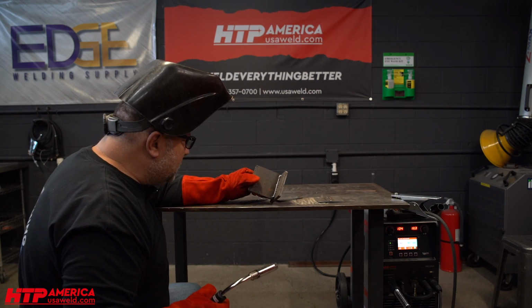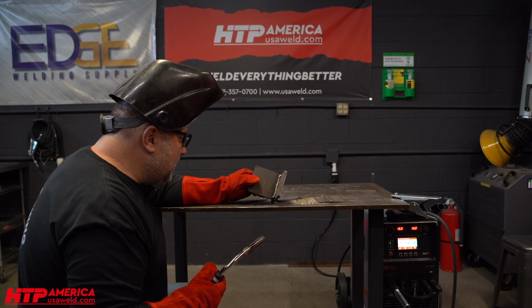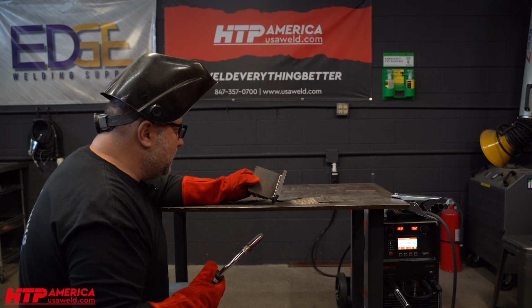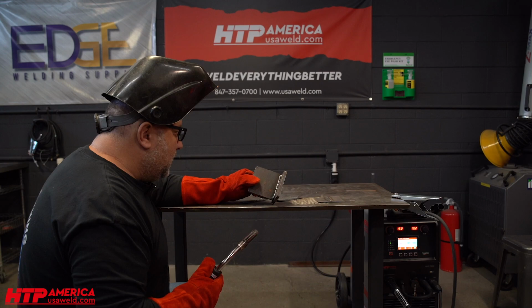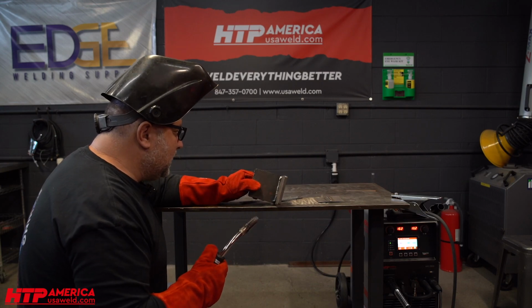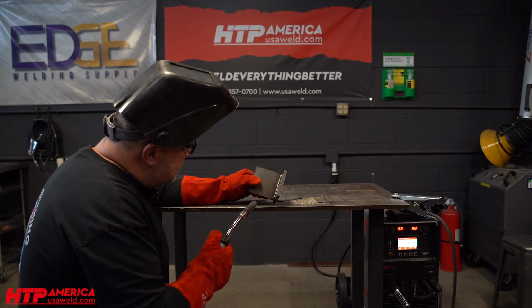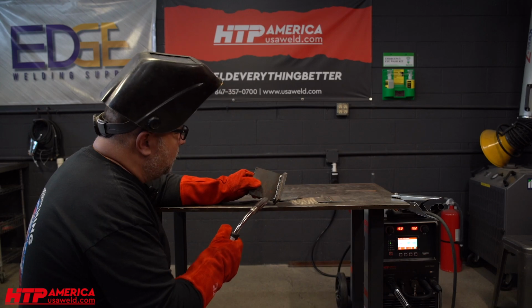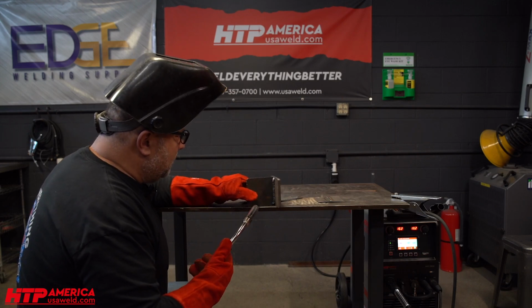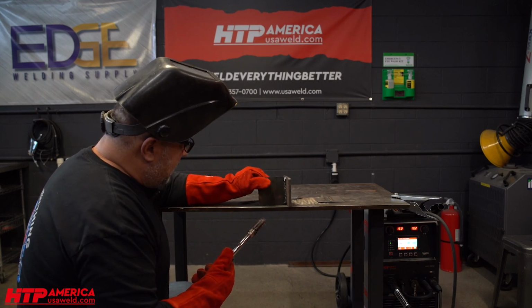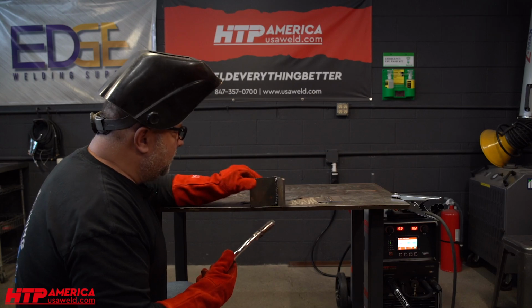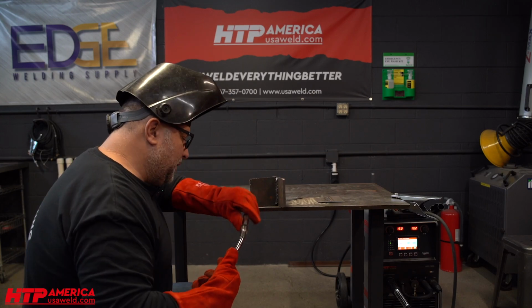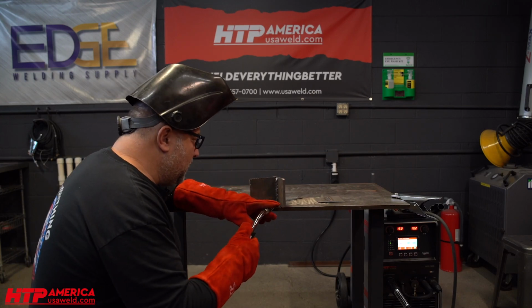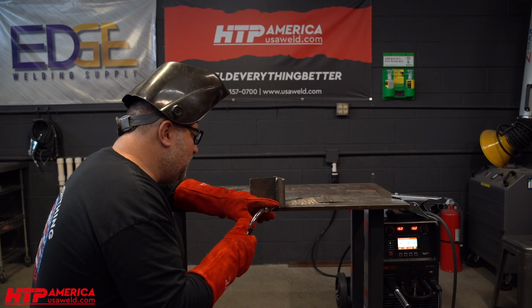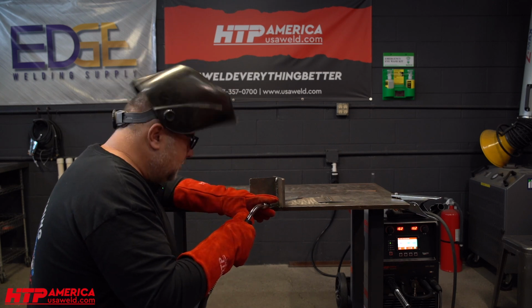So when you look at this, it already looks like I was very ambitious, had a lot of wire feed there. It doesn't look nice and smooth. That's your root pass. I know I have good penetration in there, but my toes are really cold. The second pass should smooth this out. I probably should limit it to about 250, no more than 270 inches per minute going vertical up, but I'm at 283. I'm going to try to wing it now.